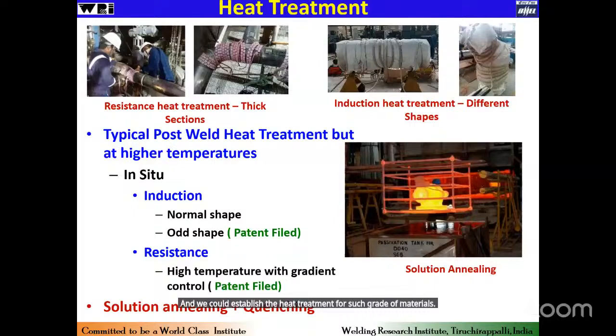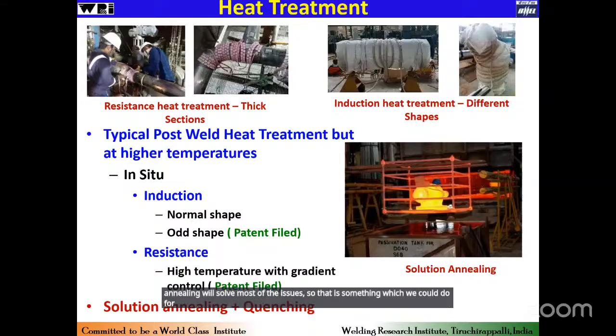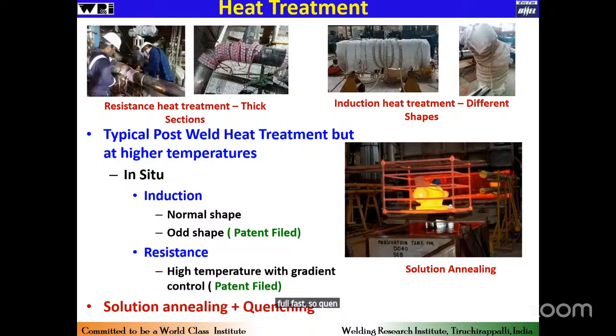And as I said earlier, in certain applications, when the combination of materials is so different, we will not be able to do a single heat treatment to cater to the requirement of the final application, so we have to go for solution annealing. And one advantage these austenitic grades of materials bring is that solution annealing will solve most of the issues. So that is something which we could do for three different grades of austenitic stainless steel. As you can see, on the right side, it has been heated to a high temperature and it has been cooled fast. So quenching has been carried out.